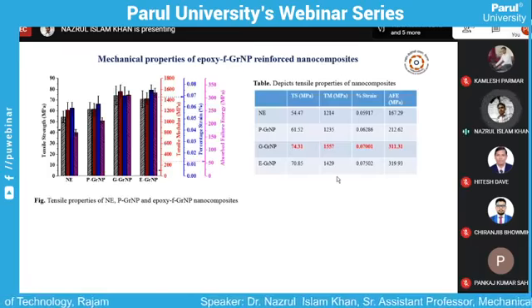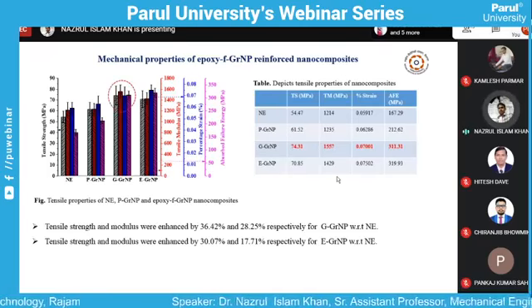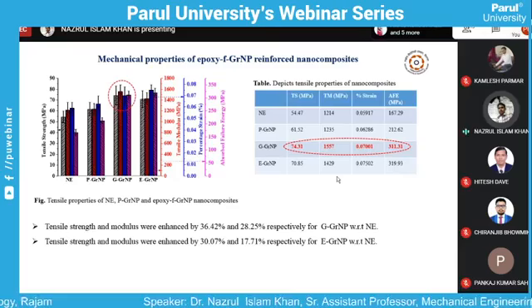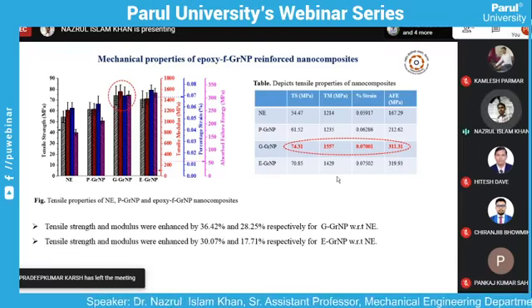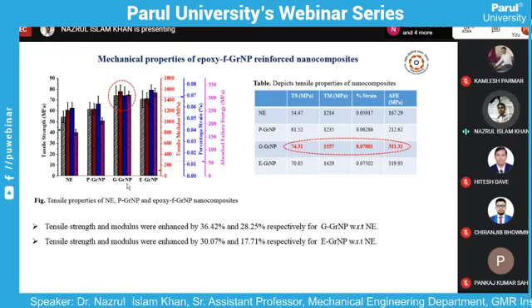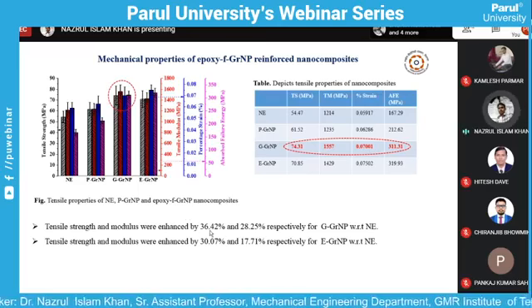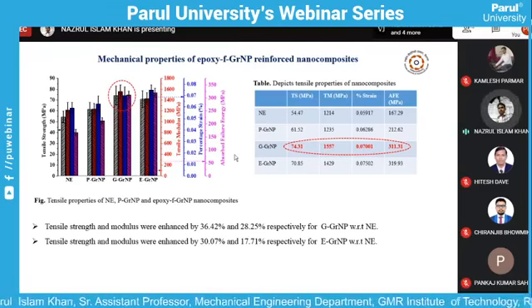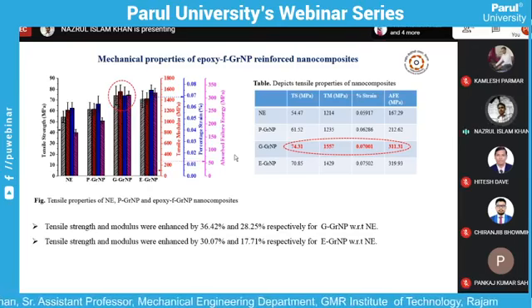This is a very simple tool. So due to the functionalization, before applying them for the next step, we first prepared some composites and tested their mechanical properties, and found that GPTMS functionalization has the capability to increase tensile strength by 36% and 28%. So first we got confirmation from physical characterization that successful functionalization took place, and from mechanical characterization we got further indication.